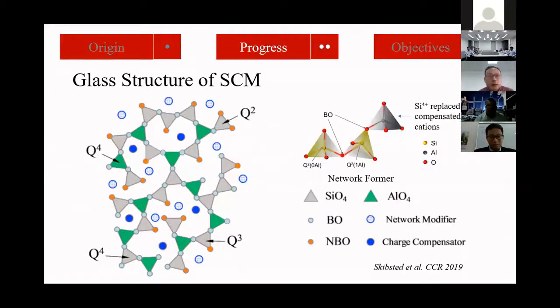So SCMs like blast furnace slag and fly ash show basic similarities. The most reactive component of these two SCMs is the glass phase. For slag, more than 90 or 95% is glassy phase, but for fly ash it ranges from, for example, 50% to 90%. It depends on the coal mineral, and also on the heating history. So in general, they share a kind of glass structure.